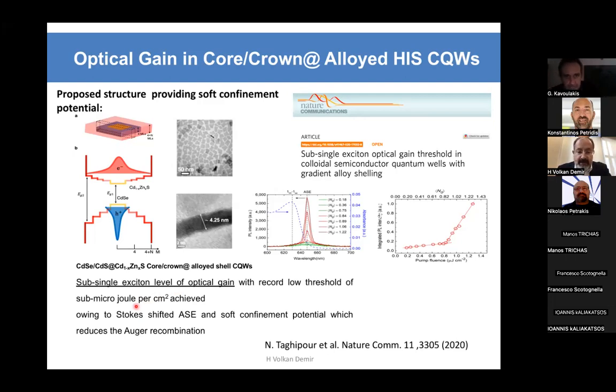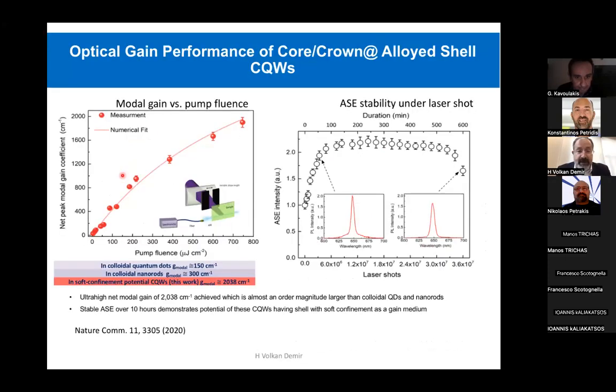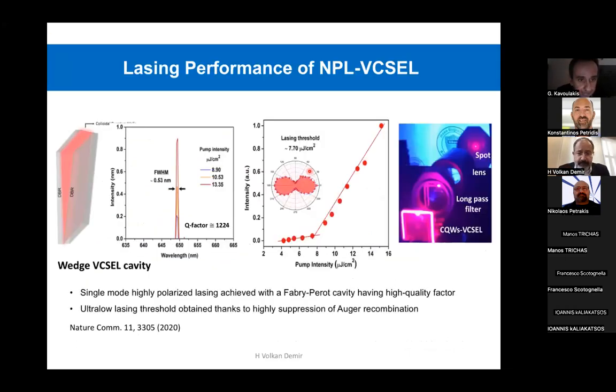This was then the lowest gain threshold possible to observe in the film in solid state, thanks to, again, both this quasi 2-dimensional structure, core crown shell, but then having an alloyed structure. Of course, one can expect this type of material should also correspondingly have high stability under very strong pumping as seen here. And you can make also, for example, vertical cavity surface emitting lasers, as we have done in a vertical DBR structure using a pair of them.